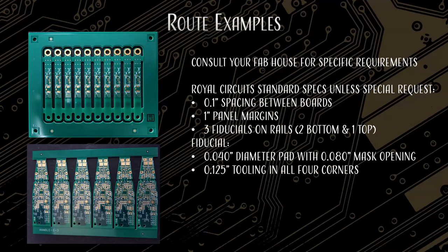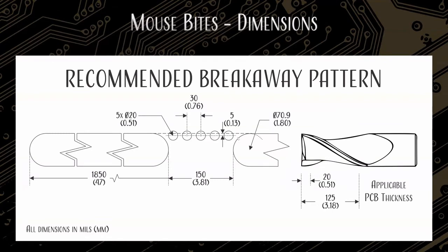There's a question: if you mill the boards out, is there any reason to use mouse bites? If you're milling them out, honestly no — there's no reason. It might give you a guideline to where to cut, or make it easier. Going back one slide: is there any reason for the 5-mil offset specifically? Could I use a 10-mil offset? Five mils is just what's worked best in our experience. You could go 10 in — that's the max I'd want to go — because then you're breaking into the board more than you want, risking delamination and splitting the dielectric between the layers. That's an empirically derived number.